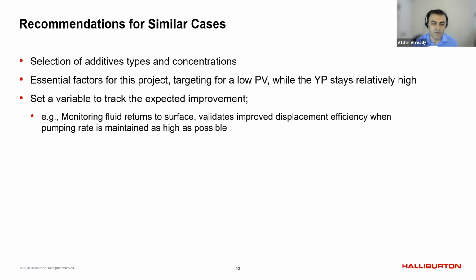And I could see recently on one of the geothermal, they had concern with losses. At the same time, they didn't want to have any lost circulation material to close the like pores. Probably holding cement or keeping the thixotropic property of the cement that prevents losses. At the same time, you're not adding like additional pressure downhole by reducing the apparent viscosity. That helps with loss of circulation. And that could be one of the applications for any types of cementing job.